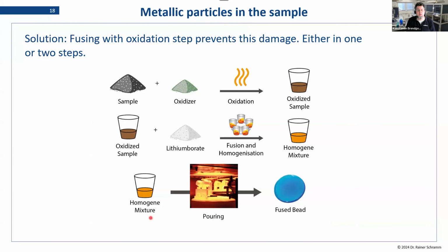So how can they be done in fusion? Well, same as we have mentioned in some of our other webinars about metallic samples or metal alloys, you do the oxidization before. So you can see here our adjusted principle of fusion. We mix a sample with an oxidizer, we oxidize before, and then this oxidized sample gets mixed with the lithium borate to do the fusion. There are multiple approaches here, and this has all been discussed somewhere else. Generally speaking, you can do it in 2 steps or in 1 step. Depending on your equipment and sample, there are different advantages to both approaches. But generally speaking, we oxidize the sample before we do the actual fusion.